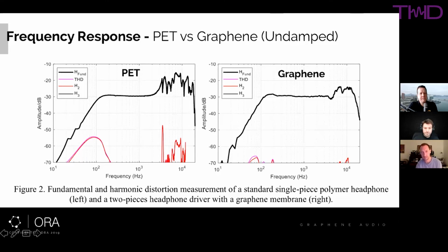With our membrane, it stays rigid up to about 11 kilohertz. The first harmonic of that 11 kilohertz is above 20 kilohertz. So in the audible domain, we get a very smooth response that doesn't have the same amount of breakup. And you see it in the harmonic distortion down here. The first major breakup mode of this PET membrane is at just over 3 kilohertz, and then you have a whole bunch of harmonic breakup frequencies that exist above that,